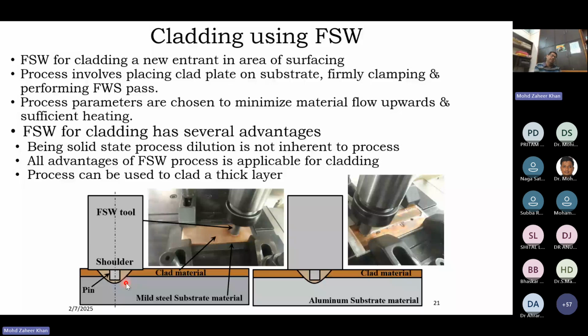On the other side, if the pin length was excessively high, then during the friction stir processing, the substrate material, which was mild steel or aluminum, would have been stirred and come to the top of the clad material, mixing with the clad material even at the top surface. Our inherent objective would not have been achieved, because we wanted to keep the substrate material inside and ensure that no contact takes place between the substrate material and the top. So after several trial runs, we could decide what should be the length of the pin that has to be used.